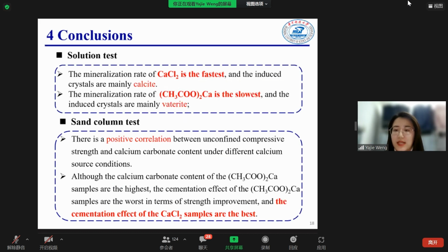From the sand column test, we know there is a positive correlation between the compressive strength and calcium carbonate content under different calcium source conditions. Although the calcium carbonate content of the calcium acetate samples is the highest, the cementing effect of the calcium acetate samples is the worst in terms of strength improvement, and the cementation effect of the calcium chloride samples is the best.